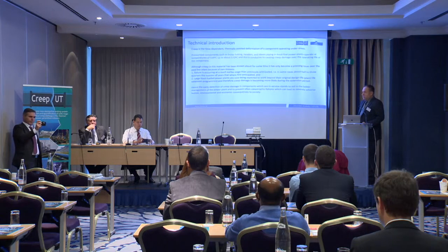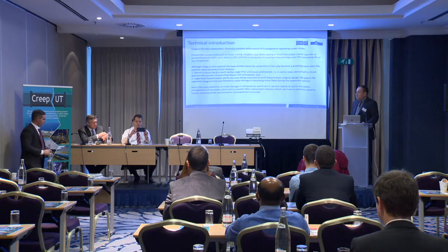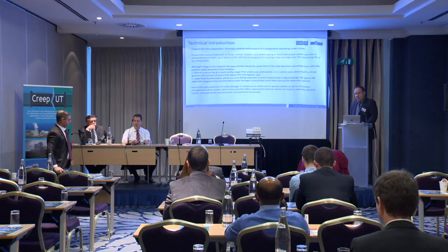So, a short technical introduction. Creep is a sort of damage that happens in power plants, in pipes that are working under high temperatures and high mechanical pressures. Typical temperatures in such plants are above 540-50 degrees, and with the mechanical pressure and such high temperatures, the steel suffers deformations that have different phases, and if you keep it long enough under such pressure and temperature, the pipes can crack and cause very large financial, security and safety problems.